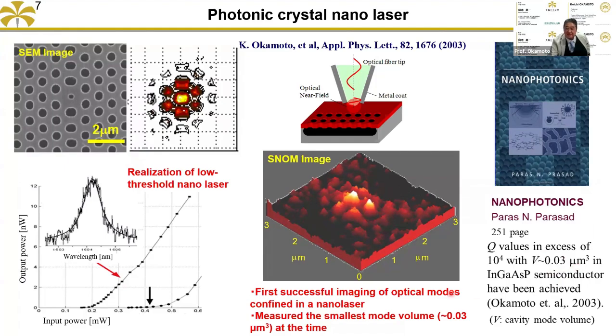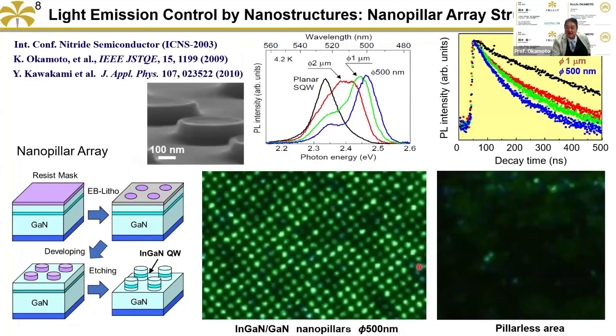Okay, then, in a similar way, using etching technology, we fabricated the nanopillar array structure for the indium gallium nitride light emitting semiconductor material. And the important thing is these two pictures were taken under the same condition. You can see the nano-fabricated region is very bright.